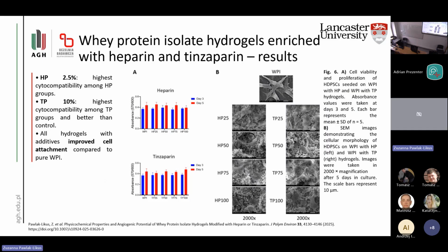Here are some results from our biological assessments. On the left, there is cell viability and proliferation of human dental pulp stem cells that were seeded on hydrogels, and absorbance values were taken at days 3 and 5. What is important from this diagram is that none of our samples had any cytotoxic effect. All of them were cytocompatible. And for heparin, the 2.5% had the highest cytocompatibility, and for tinzaparin it was 10%.